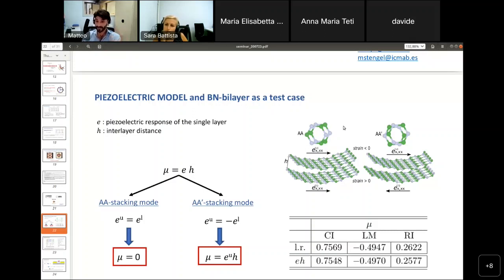So here we find that the kind of stacking is very important, and that's why it is also related to the symmetries that I mentioned before, because the kind of symmetry, or better, the lack of symmetry of the materials considered is very important. Indeed, we can see that when we bend the material, basically the upper layer, where U refers to upper and L to lower, feels a negative uniform in-plane strain, while the lower layer feels an expanding strain. So the overall effect can be written as the sum of the two single effects,